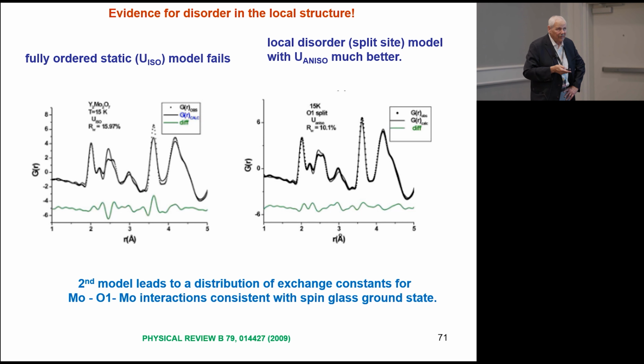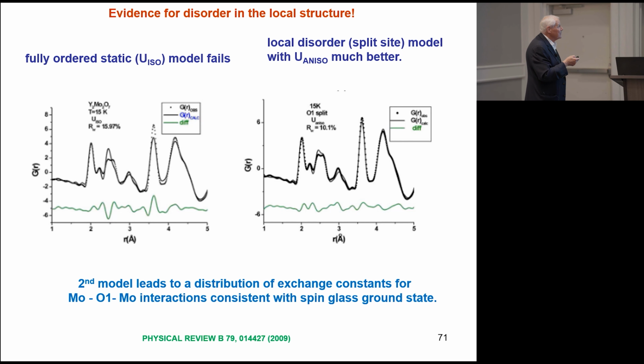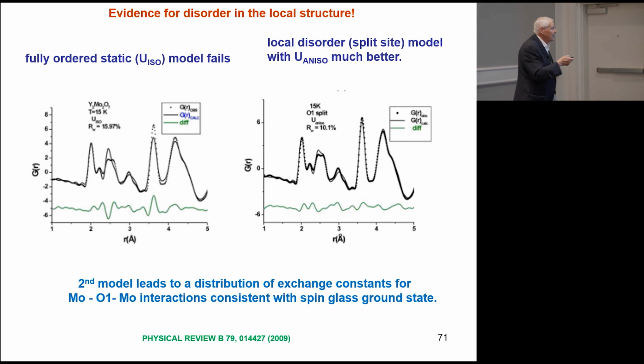At this stage of development of the analysis tools for NPDF, or total scattering, the large box RMC methods were just under development. So we were using small box approaches, and of course we tried to model the G(r) with the fully ordered static model, and that fails miserably. We knew it would. So our best approach was to try a split site model. The oxygen 1 atoms are normally in a 48-fold site, so we split them into a 96-fold site. We had some extra parameters to work with, and of course we got a better result. But again, at this stage we weren't able to apply the full power of the RMC methods.